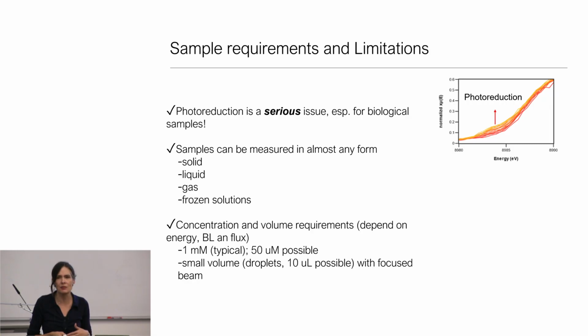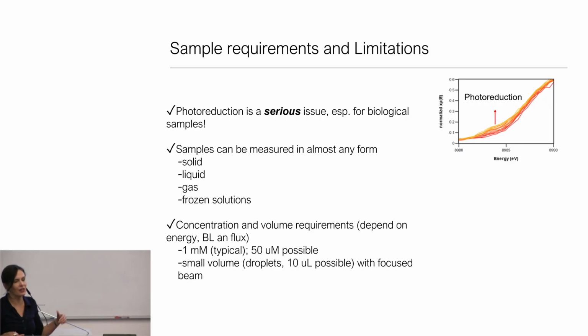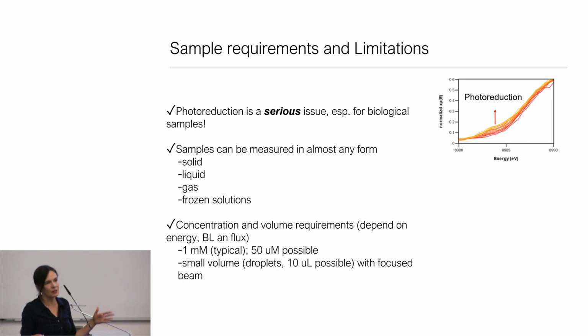That said, they become incredibly heroic experiments with limited beam time. So most of the time, go concentrated if you can, because you'll get data faster. If you have a heroic reason you need it, then one can think about how to design that experiment. We can work with relatively small volumes on certain beamlines. There are setups that deliver droplets, and one can start to think about microliter volumes with focused beams. But standard is more like 100 microliters for our typical samples.